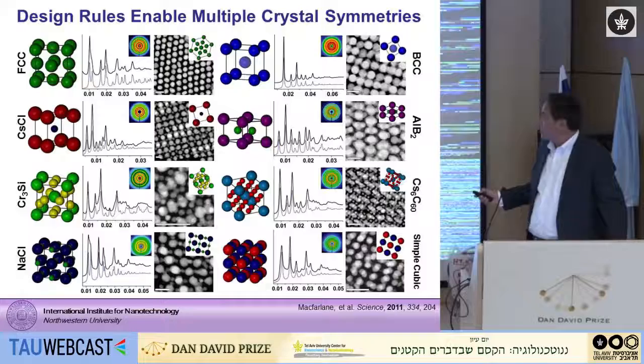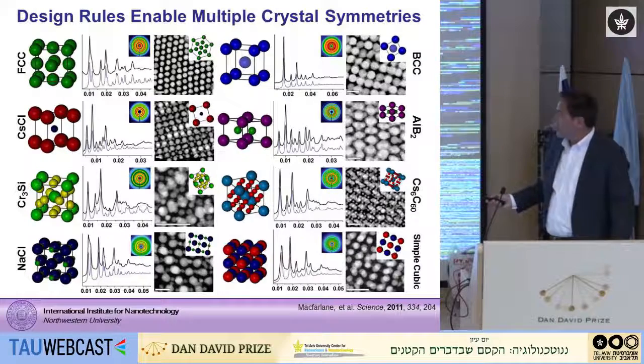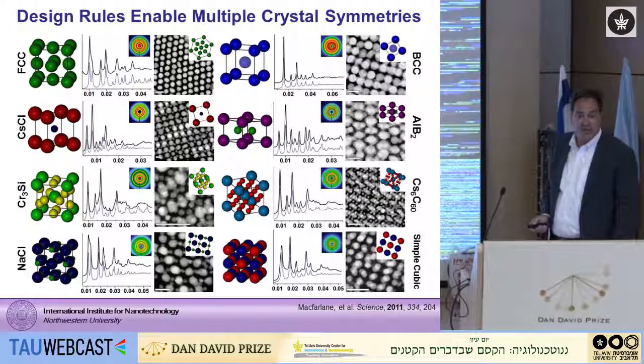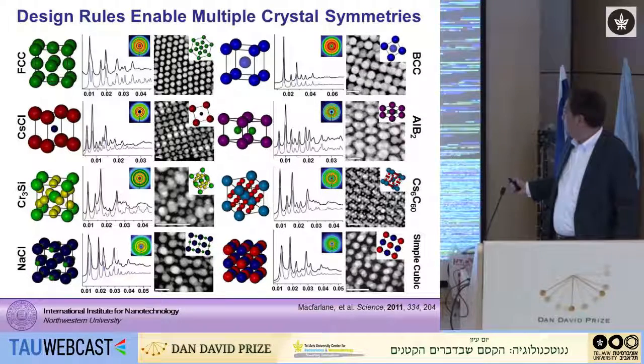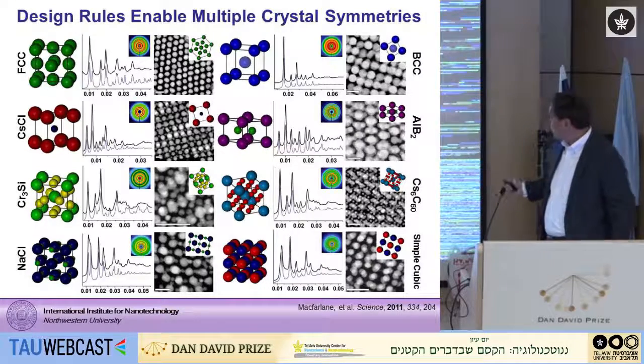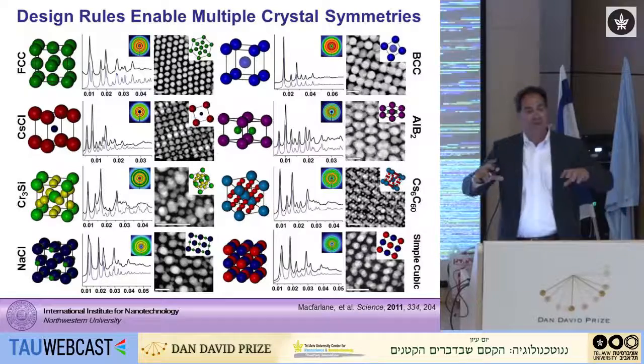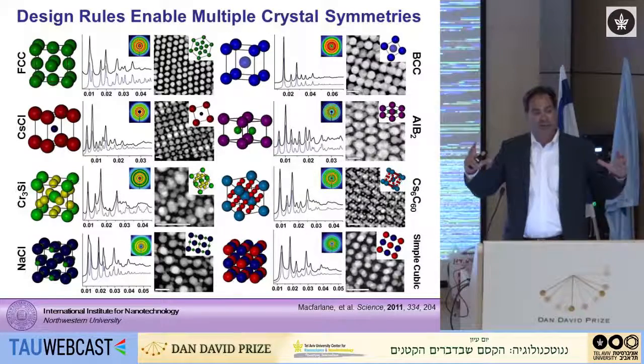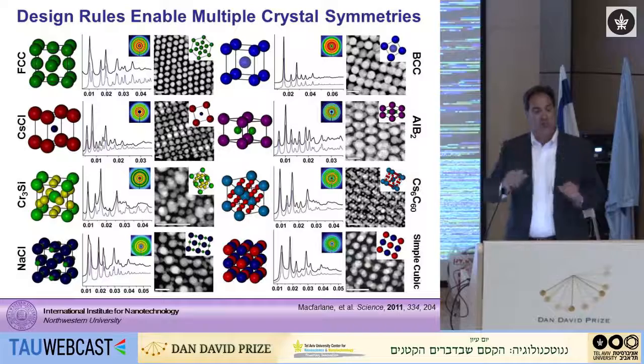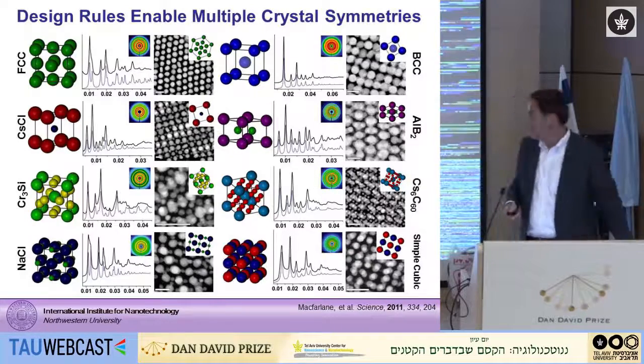So here's an FCC lattice, a BCC lattice. Cesium chloride is very similar to BCC, except you might, for example, change the particle size or identity in this case. But the design rules are quite similar in that regard. Here's AlB2, right? That's the one big and two small. You're looking at electron microscopy images on the right. These are small angle scattering patterns on the left taken at the synchrotron. That's how we characterize these structures. On the right, we're always looking at these structures after they've been encased in silica, because when you dry out these structures, the DNA compresses unless you've locked them in glass. So you're looking at them frozen in silica.